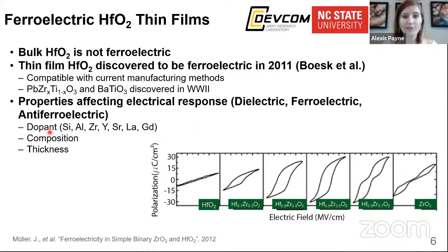Other properties that affect the electrical response of hafnia, besides going from bulk to thin film form, are dopants, what dopants you use, and how much of that dopant you use. In the panel in the bottom here, you can see that it's increasing dopant concentration of zirconia. And as you increase the dopant concentration, you can go from a linear dielectric-like response all the way to a classic ferroelectric response, all the way to an antiferroelectric-like response. And in our materials, we use alumina. Alumina is our dopant for hafnia thin films.